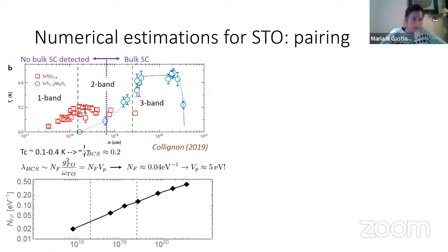And then this lambda, as I said, is going to be proportional to the density of states times some effective pair interaction, which can come from this transverse optical phonon or from any other mechanism. But at least within weak coupling, that lambda should be of this form. Then you put the numbers into the density of states, and because it's an extremely dilute system, the density of states is very, very low, in particular in this low density regime. Say the density of states is around 0.04. These, by the way, have been measured by specific heat, so it's quite well known what these numbers are.